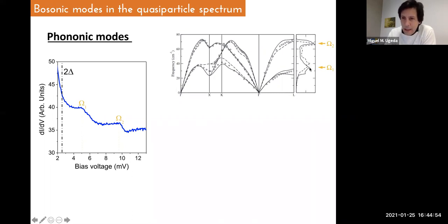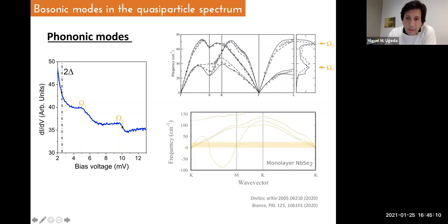And you can see there are two peaks in the phonon density multiplied by the Eliashberg electron-phonon coupling strength, the Eliashberg function. There are two peaks, omega one and omega two, that correspond in energy with these two peaks. The phonon dispersion in NbSe2 has been calculated.